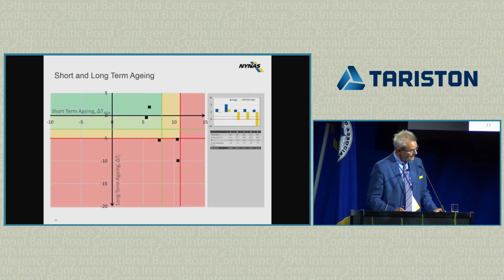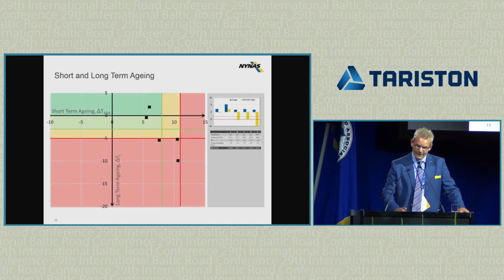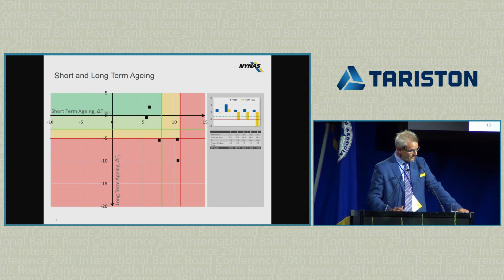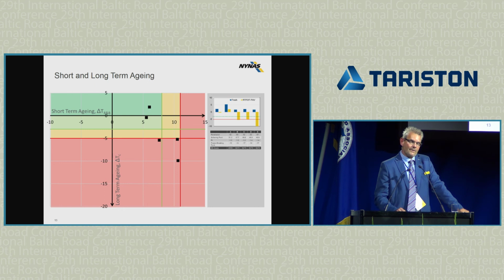Now, the next graph I've presented a little bit colorful. I've presented along the x-axis basically short-term aging in terms of changes in the softening point of a rolling thin film oven test on a standard bitumen. This is part of the European specification. If the bitumen changes in softening point is less than 8 degrees, it's okay. It conforms to the specification. If it's between 8 and 10, it depends a little bit on the grade, whether it meets the specification. But if it's more than 10, you're outside the specification, so it's red.